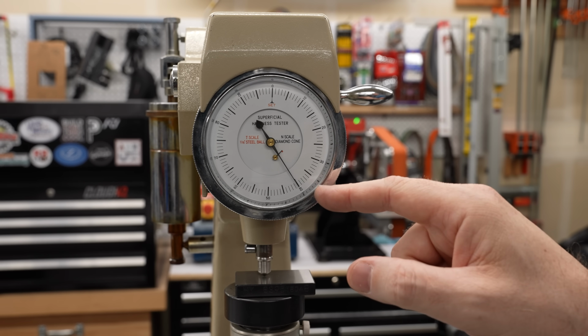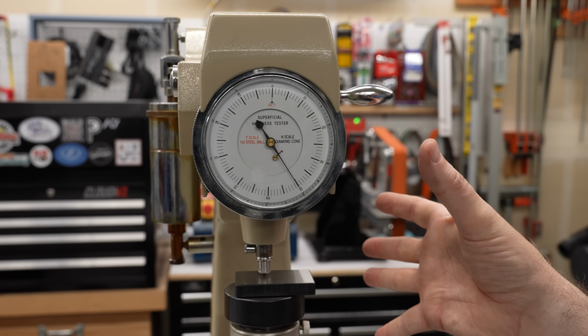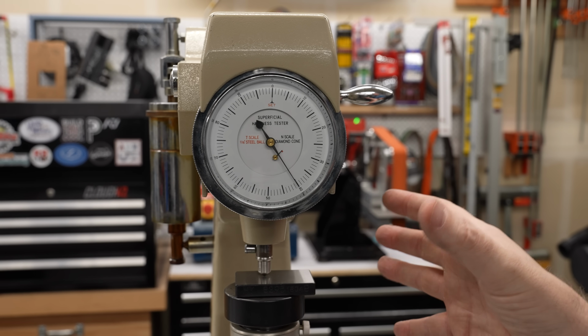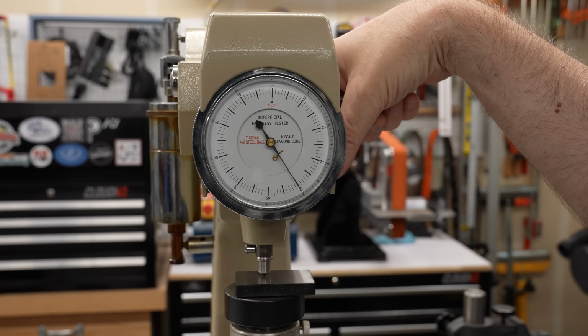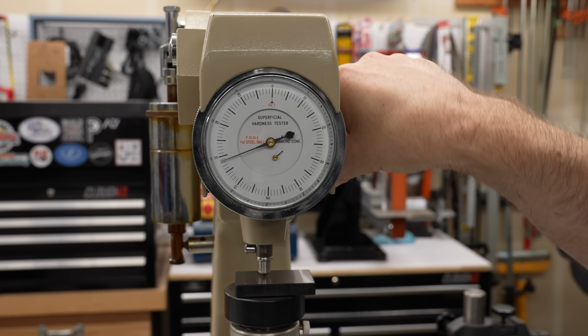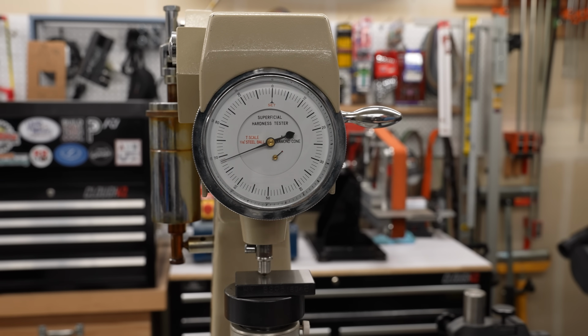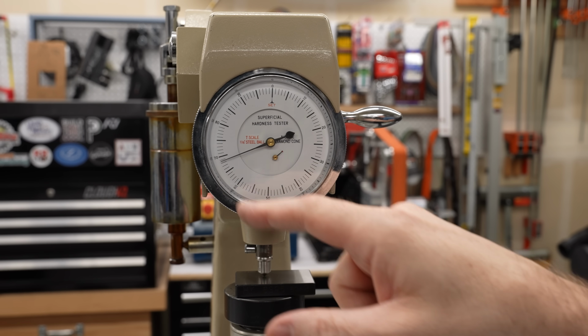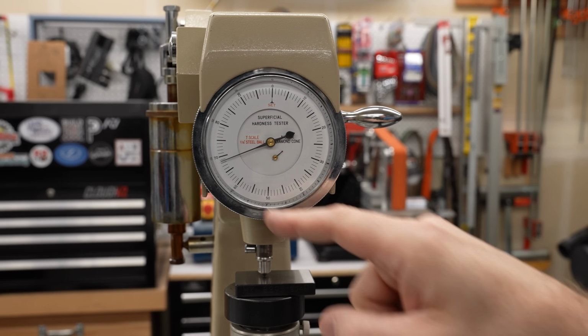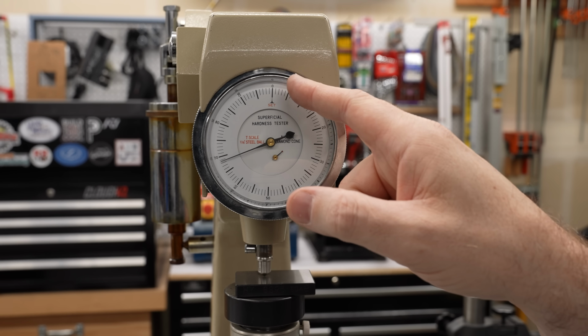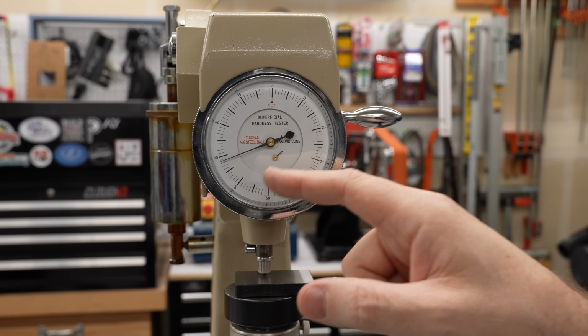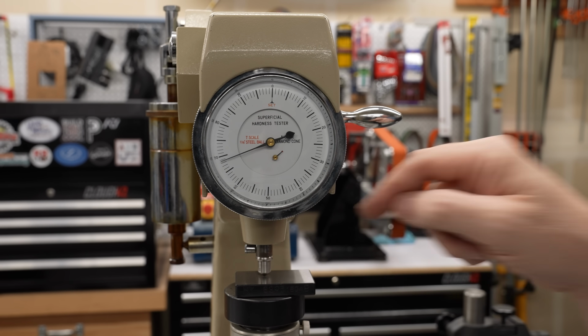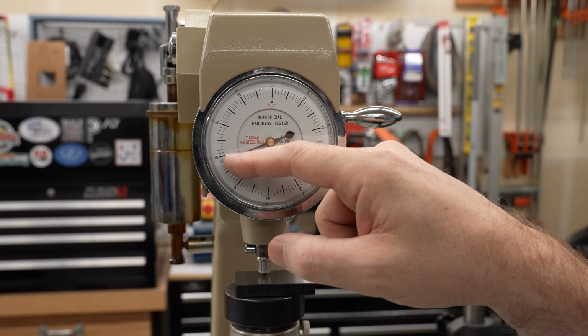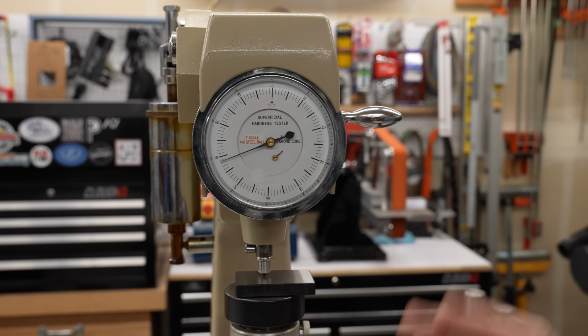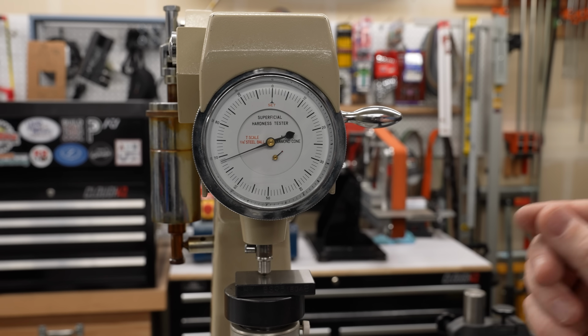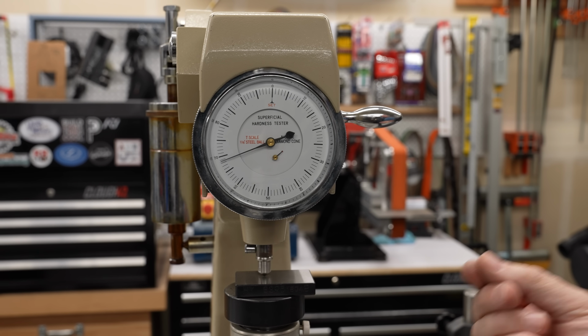But of course we can't use this value because the machine has also flexed when we applied that 45 kilos of force. So we have to lift that back off and the needle comes back up. And where we end up is at about 69. Nice. So we started with 100, we've subtracted 1,000 times D, the depth of the penetration, and we're now sitting at 69. Now that's 69 on the 45N superficial scale.